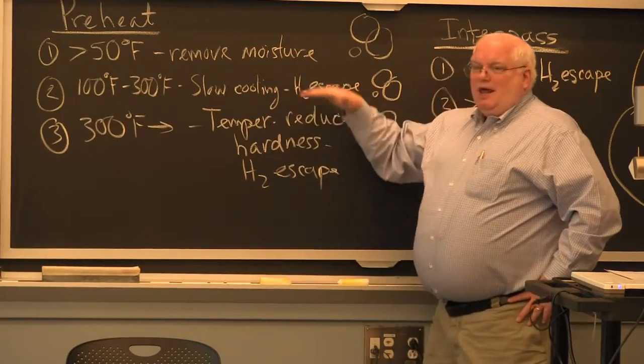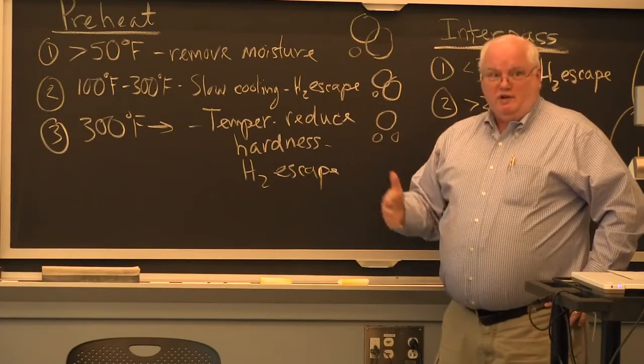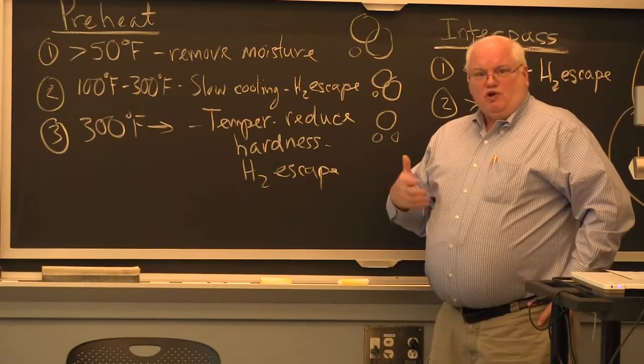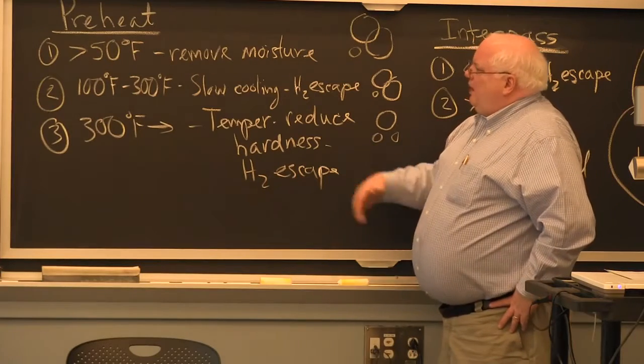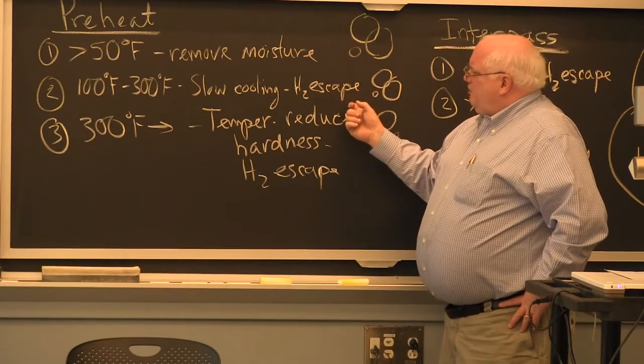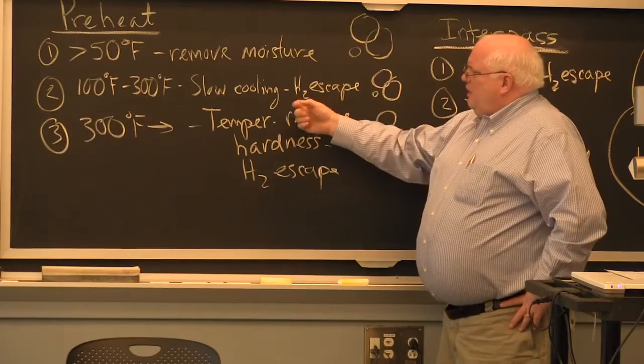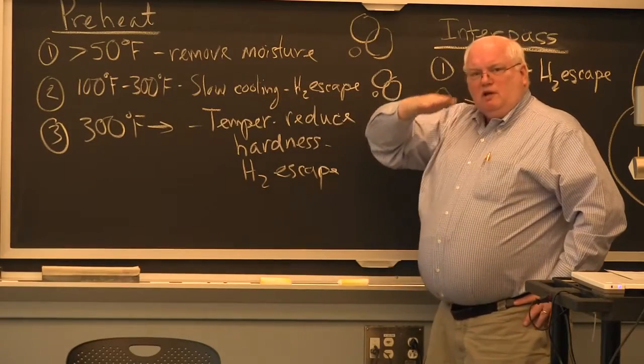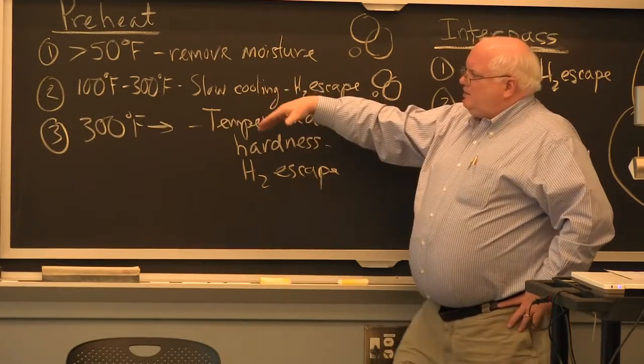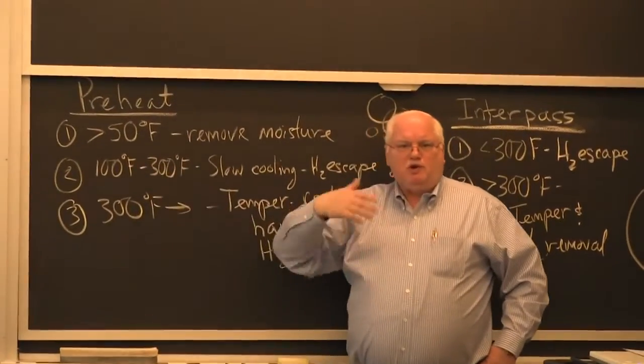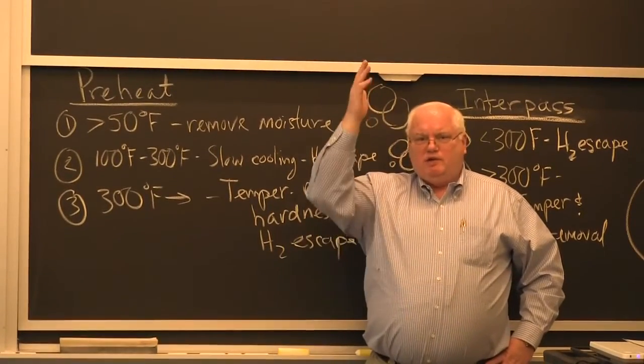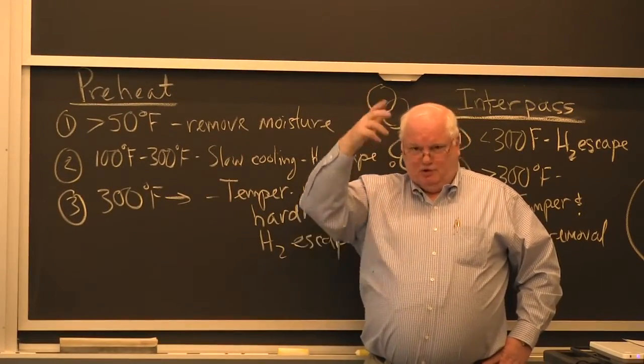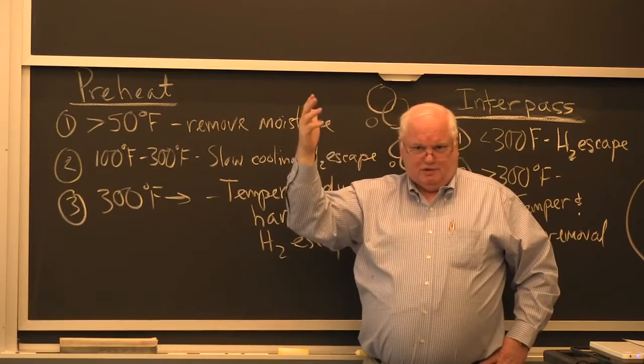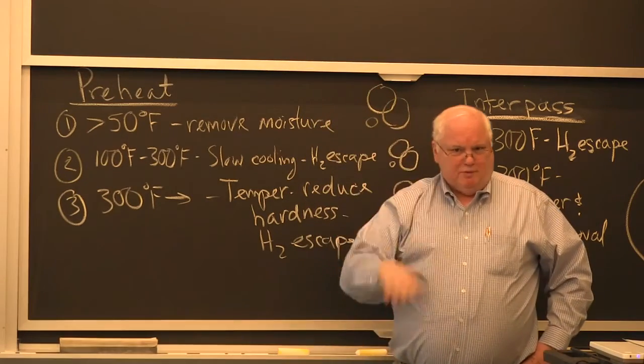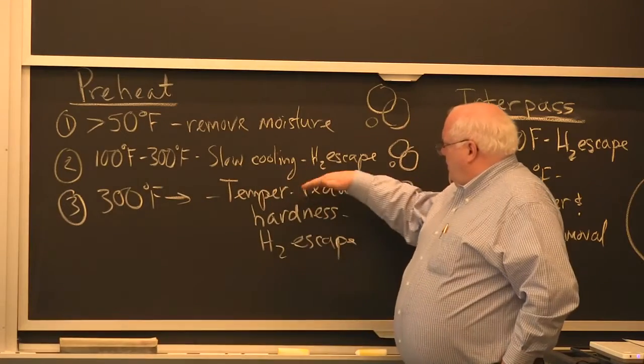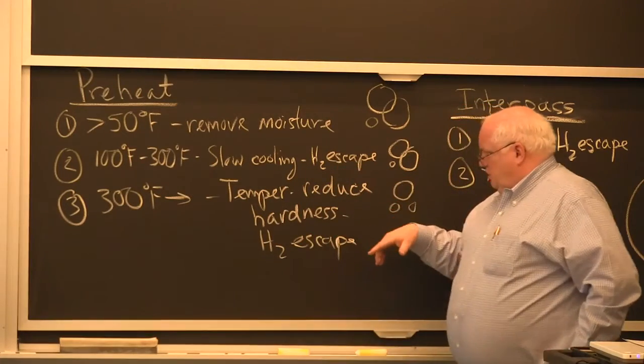Well, there is a layer of moisture even at 40 degrees, and it's more moisture than you really should be welding through. Between 100 and 300 degrees F, typically, we're just trying to slow down the cooling and keep the thing in this 100 to 300 degree range, because we know that'll accelerate the evolution, the bubbles of hydrogen coming out of the surface. And I showed you the glycerin example of that. You just speed that up, it allows the hydrogen to escape.